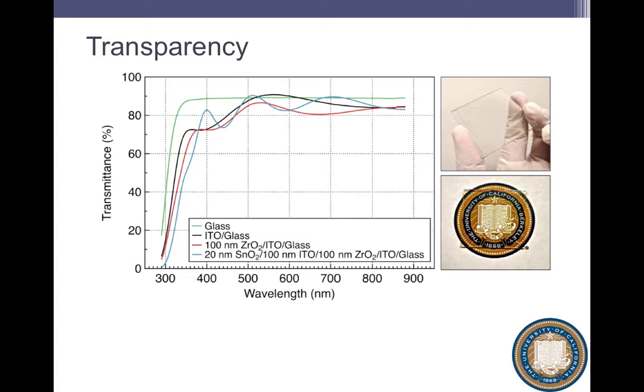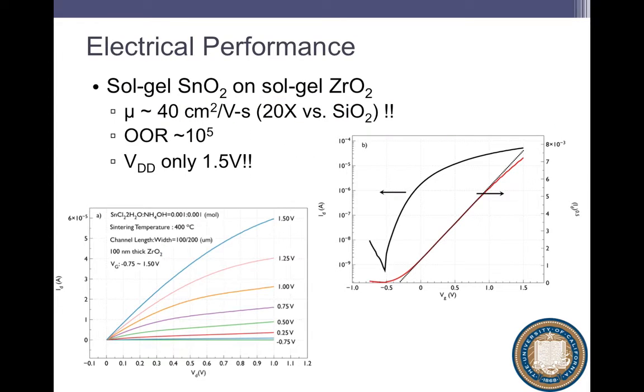So there's an array of transistors on this sheet of glass that is sitting on top of this substrate. And you can see how clear it is. It's about transparency on par with ITO-coated glass. So it really is very good. And the way we build these transistors is we use tin oxide as our semiconductor. We use zirconia as our dielectric. And the performance is really good. Mobilities of 40 centimeters squared per volt second. The temperatures that we need to process these are about 400 degrees Celsius.